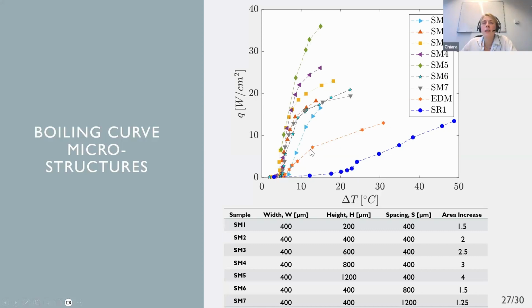Another interesting thing that we wanted to investigate was whether the effect of the machining itself on the surface had an impact on the boiling. So we also machined a sample without microstructures, but with the same surface finish from EDM, electrodischarge machining. So this orange line with stars is a sample without structures, but with a different roughness obtained by electrodischarge machining. And in fact, the roughness is enhanced compared to the smooth one by almost 20 times, showing an improvement of heat transfer.